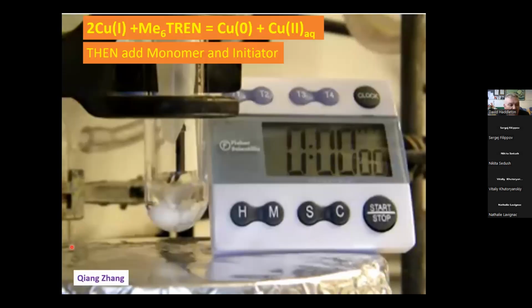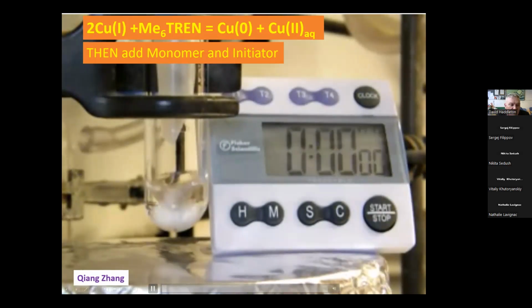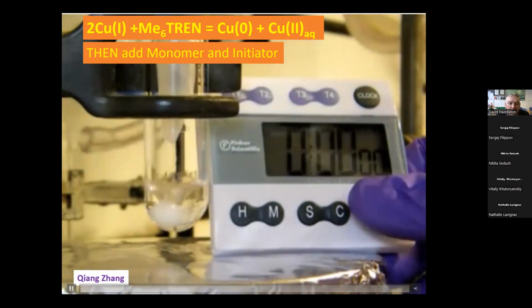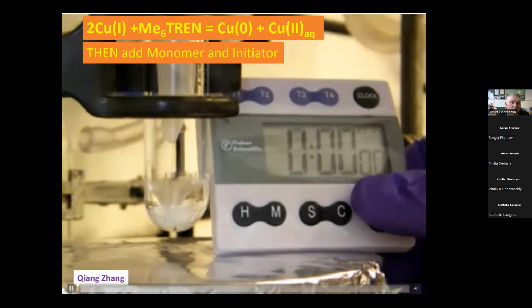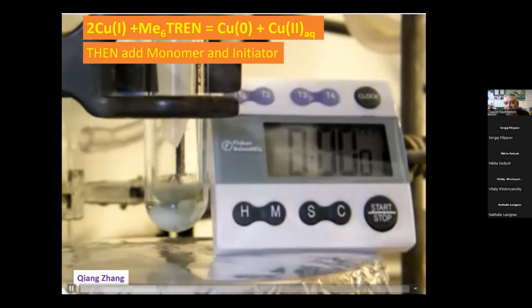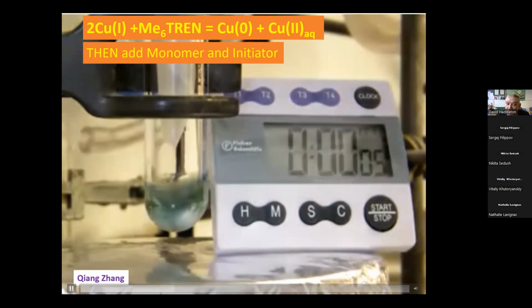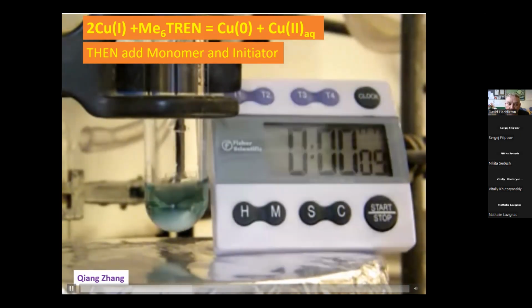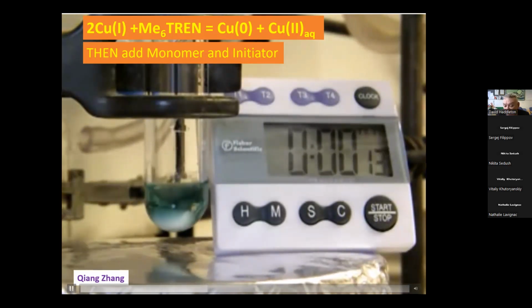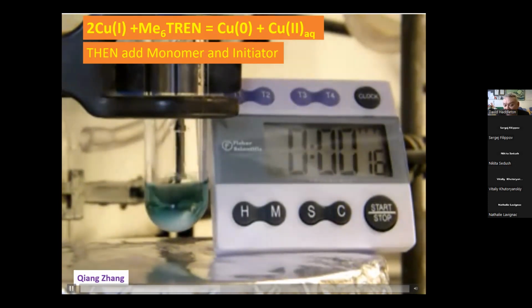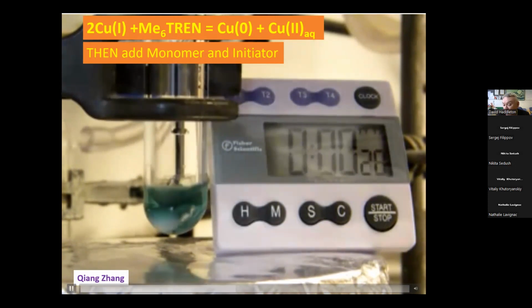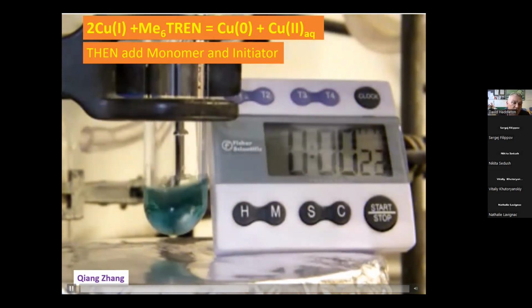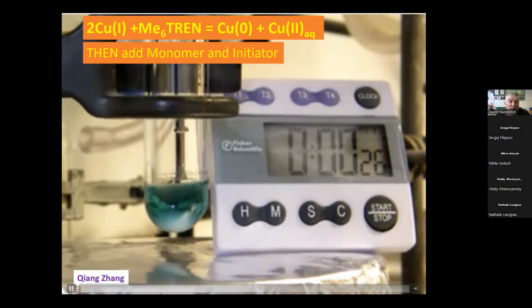And let me see if I can get this to work. So what you're seeing here is a solution of hexamethyl tren in water. I don't think any sound's coming on this, so that's okay. And then when the button's pressed in real time, some copper 1 bromide has been added to that solution. Now, again, if you remember your inorganic chemistry, copper 1 is white. Copper 1 is not blue. Copper 1 is not green. It's D10. And the colors of transition metals are because you have an electron missing. So copper 2 is D9, blue or green, blue in water, green in organic solvents. So what we've seen here in 30 seconds is the copper 1 has reacted to become copper 2.